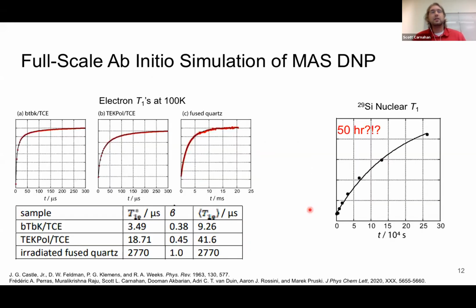As a part of this project, we measured electron and silicon nuclear T1s at 100K. And this is where we see the special properties of quartz. At 100K, the electron T1 is orders of magnitude longer than that of standard nitroxide radicals. This is one of the reasons we're able to do some special things with it. In addition, the silicon nuclear T1 is 180,000 seconds, or 50 hours, or more than 2 days. If we wanted to try and do something quantitative, it makes this extremely difficult. So waiting 10,000 seconds, or 3 hours, for one scan on the time scale of the silicon T1 is still really not that large. This is an extremely long T1.